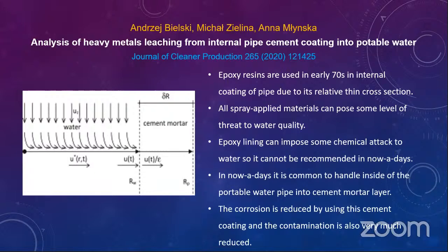Thank you, Krupakar. By referring to a recent journal on the analysis of heavy metals leaching from internal pipe cement coating into potable water, we have come to a conclusion that in the early 70s, mostly epoxy resins have been used. Some of the authors have developed a mathematical model of the heavy metals leaching from the internal pipe cement coating into potable water that included sorption inside a porous cement coating and diffusive transport into a liquid phase. The mathematical model developed by the authors was experimentally verified for static conditions where the water was placed inside the pipeline statically. A high correlation coefficient was observed between the experimental and the calculated results for chromium and lead migrating from the cement coatings into the drinking water.